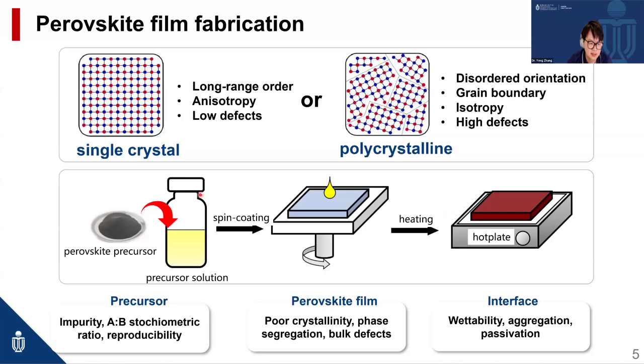In this process, the defects may originate from precursor impurity, and also the AB composite stoichiometric ratio difference could result in bad reproducibility. And the perovskite film's crystallinity and also phase segregation are important for lowering the defects.